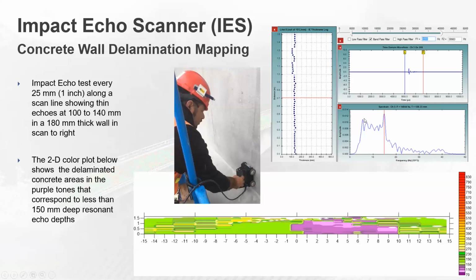So here are some example results quickly about how this can be used. Here a concrete wall was being mapped out for delamination damage. It could be front side or back side. It was a nominally 180 millimeter thick wall, about 7.5 inches. And as you rolled it up, every inch or 25 millimeters, you got an impact. So this is that actual impact at the cursor location. This is a scan from 0 to about 1.5 meters up a wall. And at this location, it's predicting a 126 millimeter echo, meaning there is cracking damage at the backside of this wall.